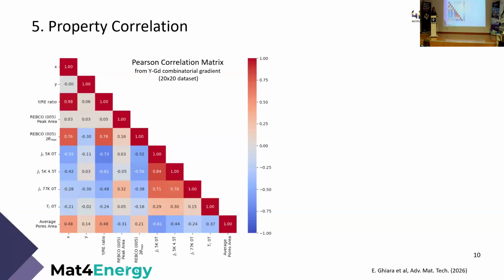So at last, from all these property maps, we can generate a property correlation matrix, which has the aim to identify the correlation between different properties. For example, here I have highlighted the fact that the rare earth distribution is highly dependent on the X location, while it's almost independent of Y, as expected by the combinatorial design. But also we can see that the superconducting properties increase with gadolinium content in this specific sample.